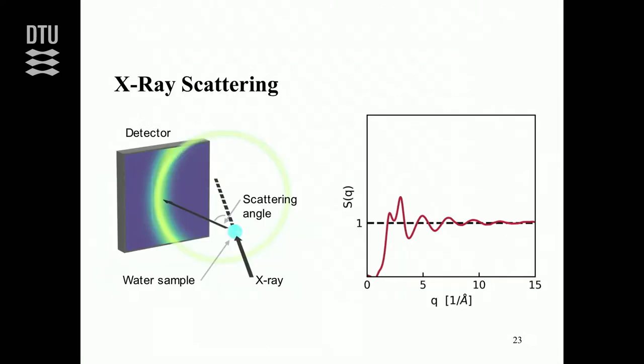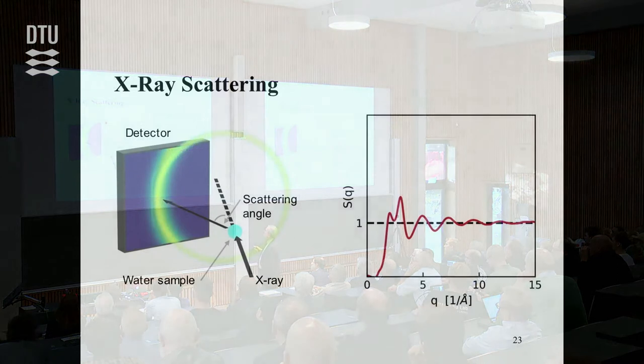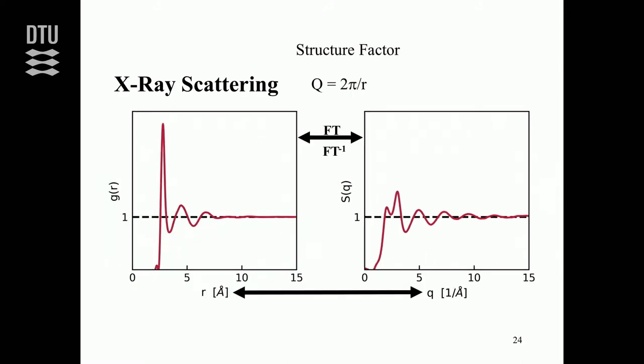And we will now start to use X-ray techniques to look into the structure of these types of materials. Some of you know X-ray techniques very well and others less. So we will come in with X-rays and then we will scatter off the sample. With this angle, we eventually call that a momentum transfer. And we will see a ring. We will not see dots as Bragg reflections from a crystalline material, but a ring when it's a disordered material. You will see this in what we call reciprocal space, and we call this the structure factor. It's in 1/Ångström. And we can convert this to real space by using what we call the Fourier transform. It's like going from reciprocal space to real space.